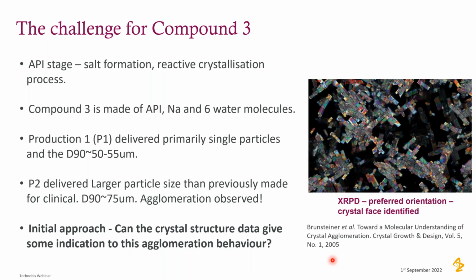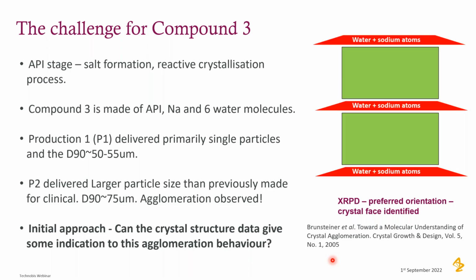So when you look at the optical microscope, you can see that these are basically nice plates. They seem to be sticking on top of each other on the largest crystalline face. And when we did XRPD with preferred orientation and using crystal face identification, we realized that this larger face is where, in red, you can see the water and the sodium atoms, and in green is where the API was. So the API is in a sandwich between water and sodium atoms.